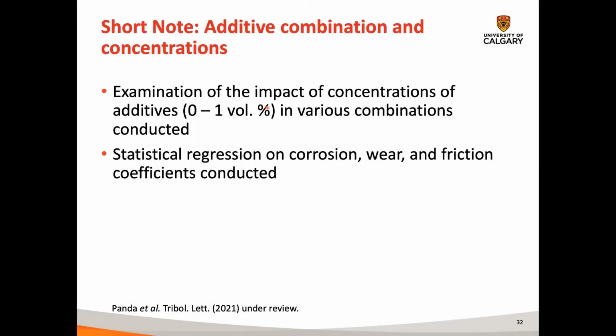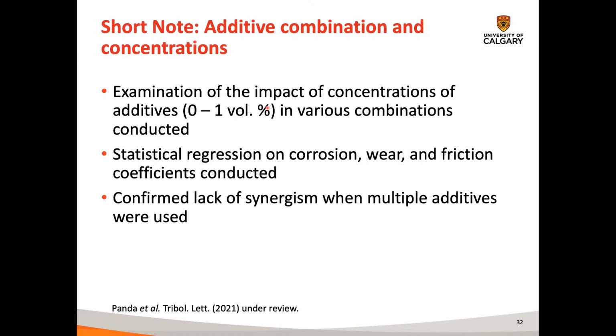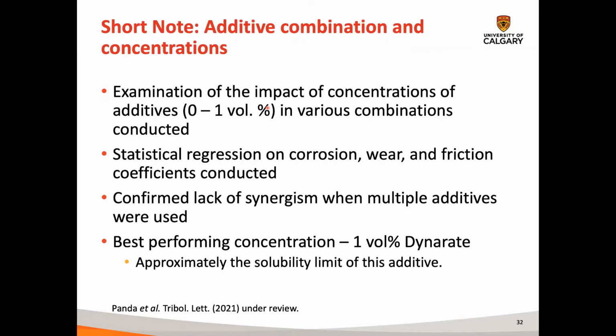And we did this statistical regression on these different parameters based on the concentration of the additives. And we confirmed that also there's no real synergism when you use multiple additives. And yeah, as I said before, Dynarate is the best additive here.